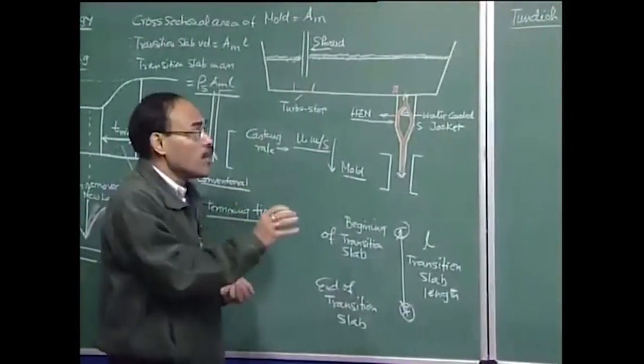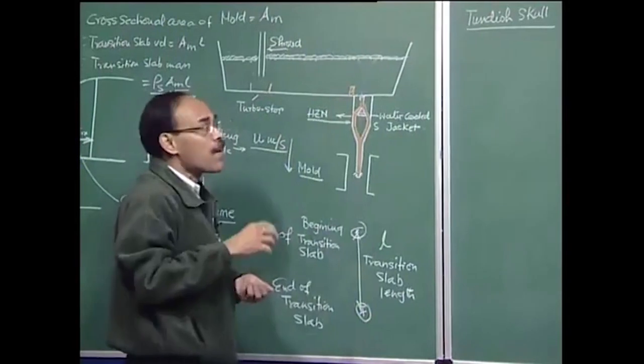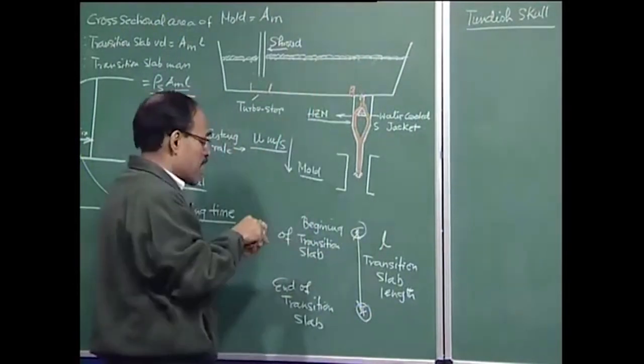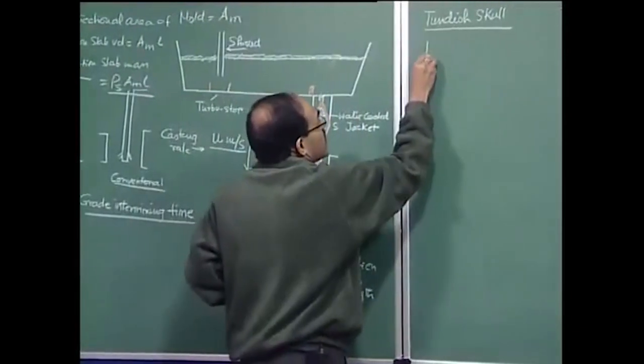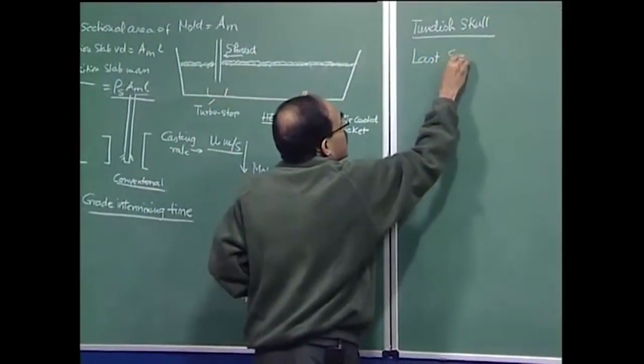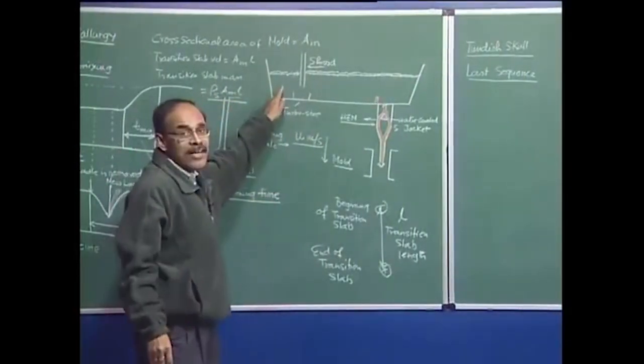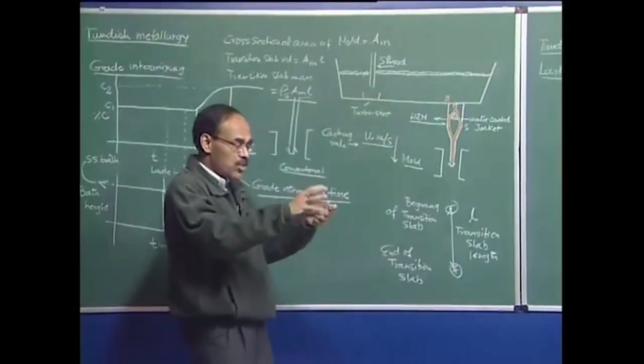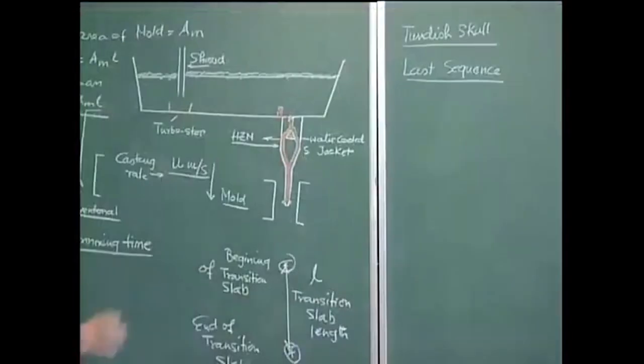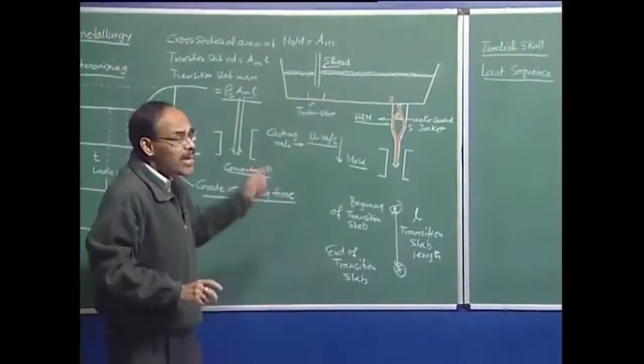If the flow rate is very high, there will be a tendency to form vortexes and drain the slag layer, because as mentioned, you can see funnel vortexes particularly when draining a sink — the higher the velocity of water from the tap, the more intense the tendency for rotational funnel vortex formation. Similarly in the Tundish, as the casting rate increases dramatically, there will be a tendency for the slag layer to be drawn down, and this is particularly prominent when the slag-metal level falls.